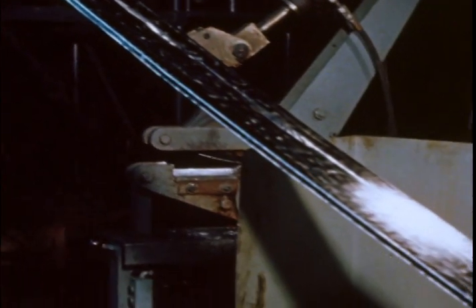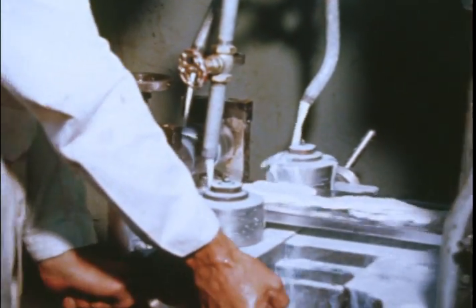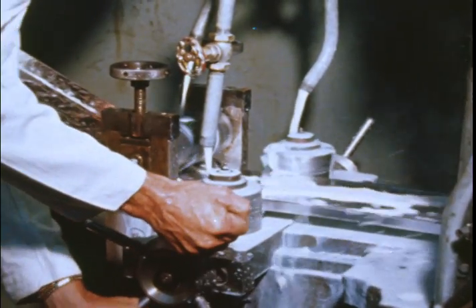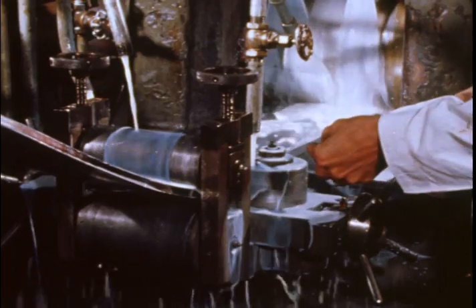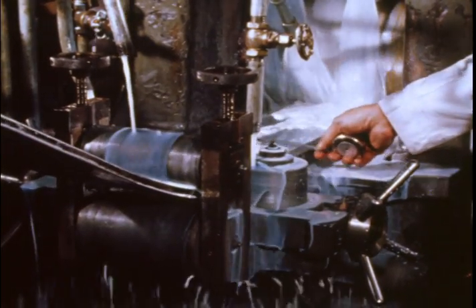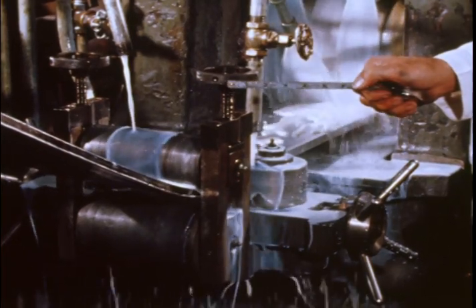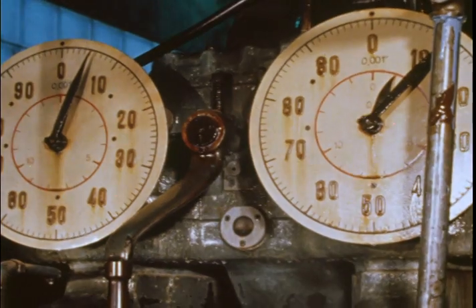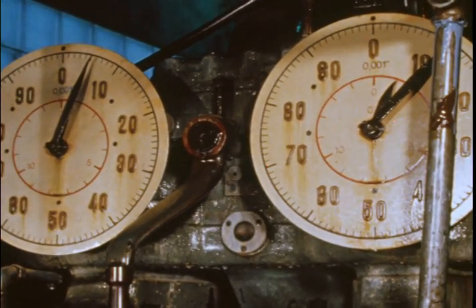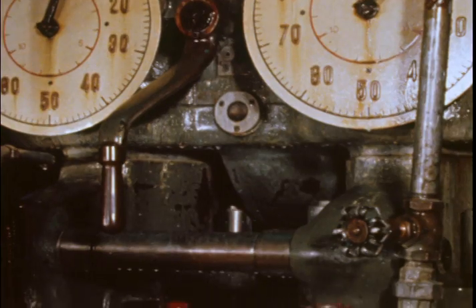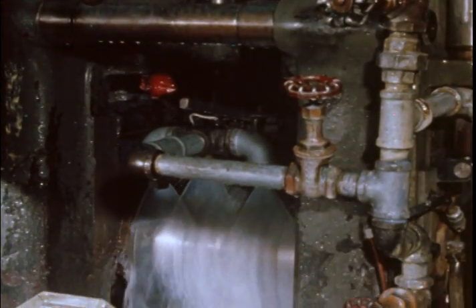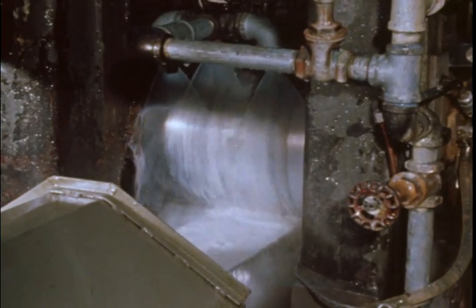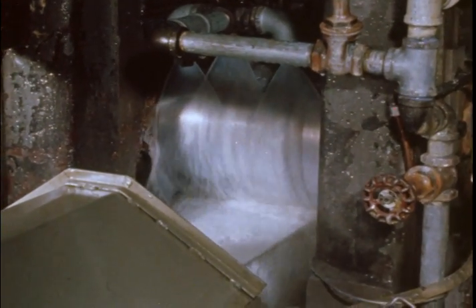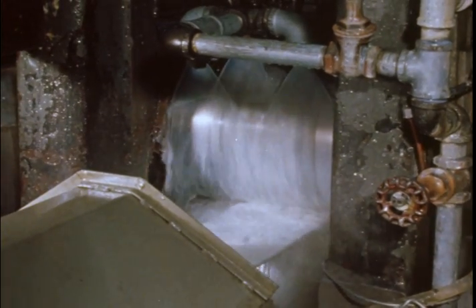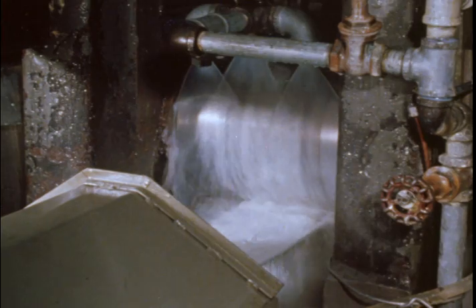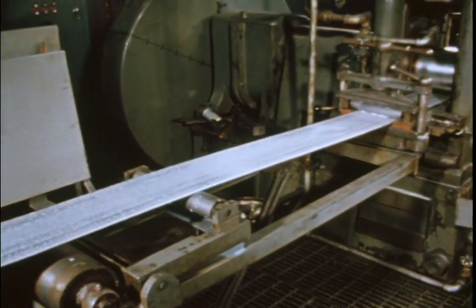This strip, which is approximately 900 degrees Fahrenheit in temperature, must now be reduced in thickness down to gauge. The first step is this hot rolling operation. The strip enters the mill 3/4 of an inch in thickness and emerges 3/16 in thickness. This white milky stuff you see splashing around is lubricating oil. It is necessary to prevent sticking of the aluminum to the mill surfaces and to keep the rolls themselves cool.